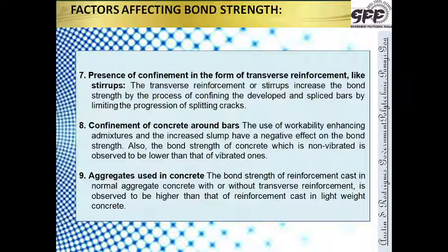The use of workability enhancing admixtures. Please note this part, very important. The use of workability enhancing admixtures and the increased slump have a negative effect on the bond strength. Also, the bond strength of concrete which is non-vibrated is observed to be lower than that of the vibrated ones. A lot of research has been done on this. The results have been published. So this is the result of those experiments.